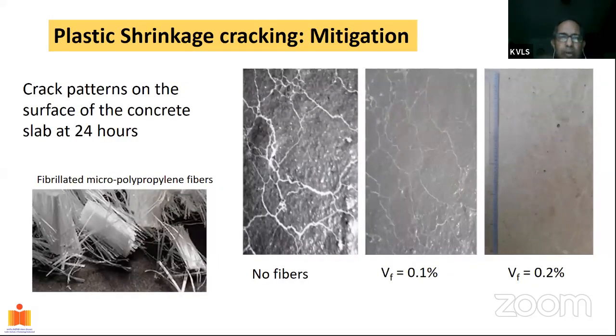Adding fibers. A small dosage of fibers basically, and these polypropylene fibers that are commercially available now cut down on these cracks that appear on the concrete surface. So I'm showing you that concrete without fibers has these surface cracks that develop, but if I add like 0.2% the volume of concrete in the small fibrillated fibers, I'm able to essentially mitigate this effect of cracking on the surface. So these fibers are also being added into concrete to control this aspect of cracking that happens because of shrinkage.